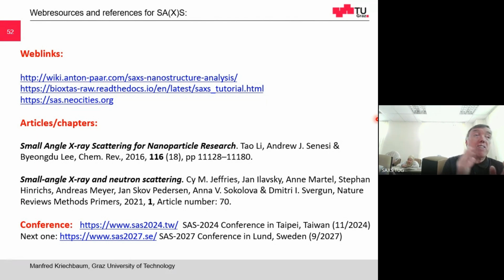You should also always use complementary methods because you don't get the absolute structure. So you should use cryo-EM or electron microscopy as a complementary method to verify your structure. And if you have a nanoparticle and you want to solve the structure, you should work more with the exclusion principle. So your model might fit like a cylinder. You just have a simulation, it fits a cylinder within the limited space. Then you should just say, okay, from my experiment I can conclude it might be a cylinder, but you cannot exclude other, slightly different models.